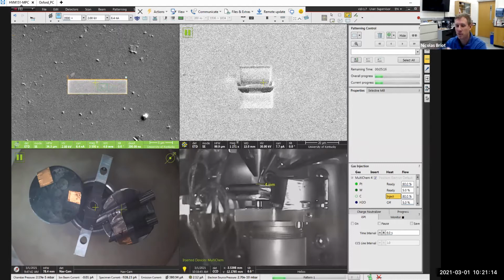So usually when you make a focused ion beam cross section, you first protect the surface a little bit with a material. You can, outside the machine, deposit a micron of something, a metal or something, or you can do it inside the system, and that's what I'm doing now. Right now, I'm depositing some carbon at the surface of the sample, just a little bit using the electron beam. So the FIB is not involved just yet, just the electron beam, the SEM. This is just to coat the surface with a sacrificial protective cap of the region I want to cut, so I keep the pristine original surface.